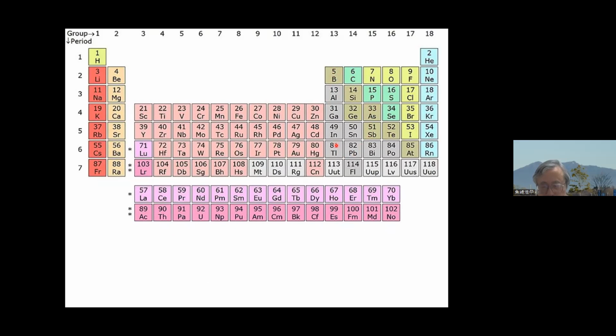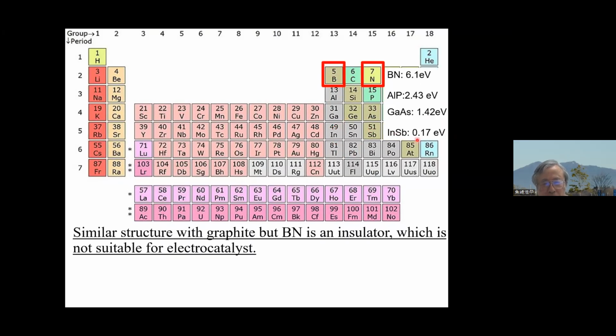semiconductor group. So indium antimony has 0.17 electron volt, gallium arsenide has a 1.42 electron volt energy gap, aluminum phosphide is 2.43. Boron nitride has an energy gap of 6 electron volts, which means it is an insulator. So boron nitride has a similar structure to graphite, but is an insulator. Of course, if it is an insulator, people easily think it is not good for electrocatalysts.